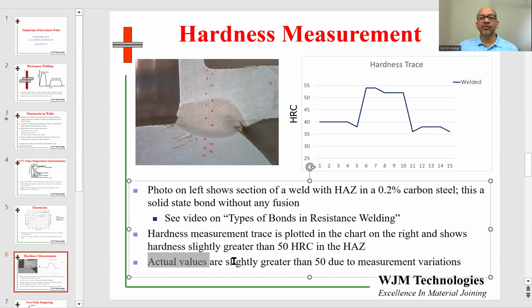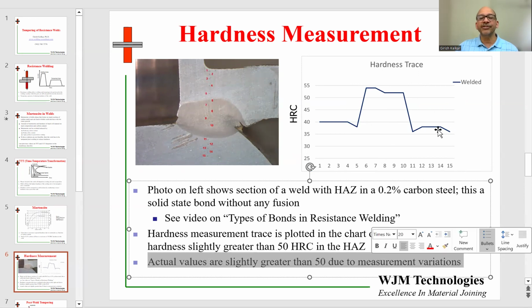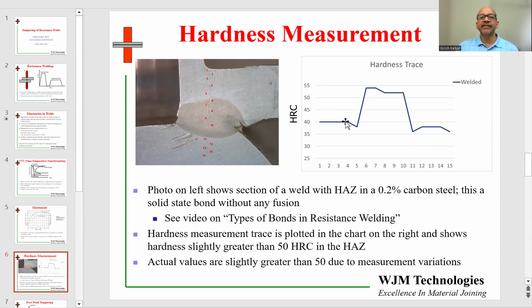Now, the actual measurements over here are slightly more than 50 because of measurement variations in those regions. And we also see that the base metal hardness is also quite high. And that is possible because some of the hardness will come from previous work hardening processes such as rolling, extrusion, bending, forming, stamping, and so on. So if that hardness is not annealed prior to welding, then the parts themselves can have substantial hardness even before we go into welding. But nonetheless, the maximum hardness is typically governed by the carbon content.